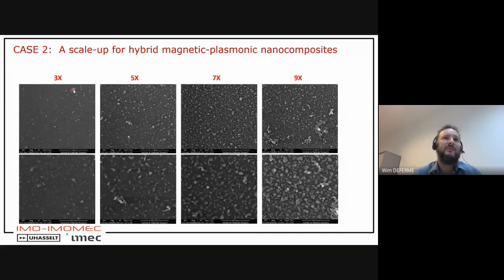The interesting thing you can see is that if you do three layers, you have a coverage which is very low. And then, of course, the more layers you put, the more coverage, the more the substrate is covered. On the other hand, what you also see is that you have some clusters. You have nanoparticles sticking together. And that, of course, is not what you would like to see. You would like to see individual nanoparticles sticking onto the substrate.